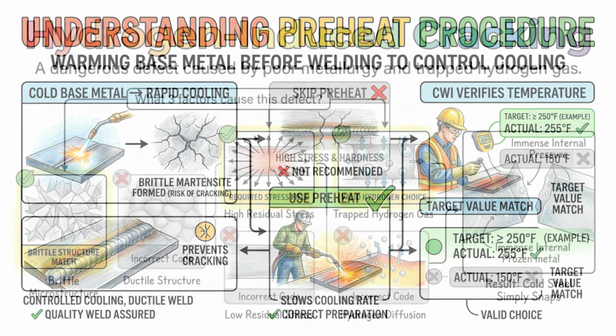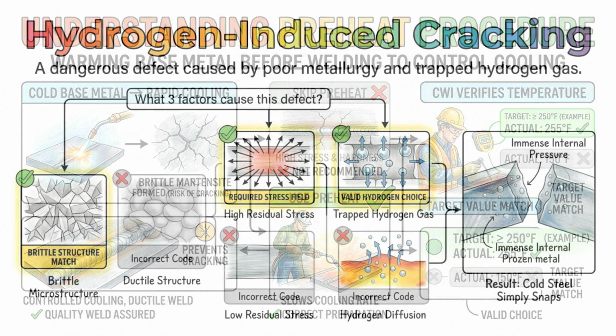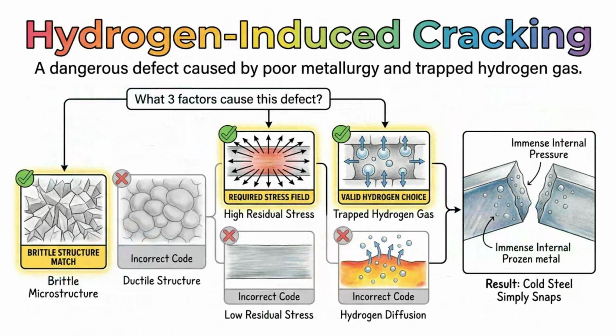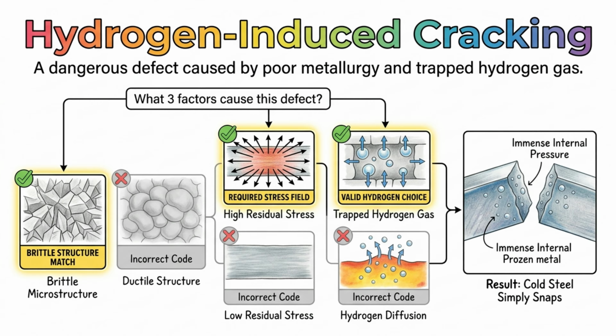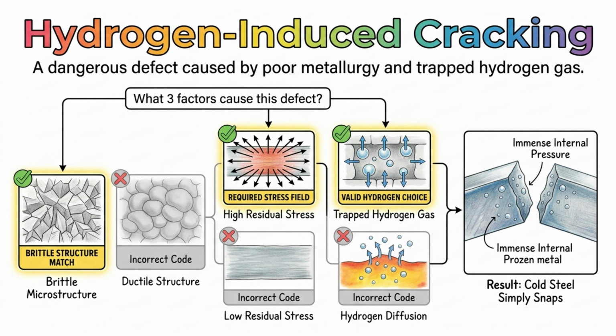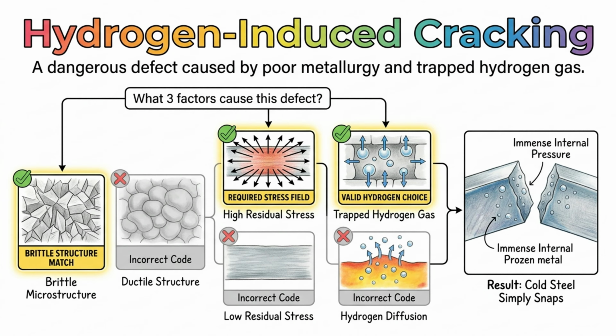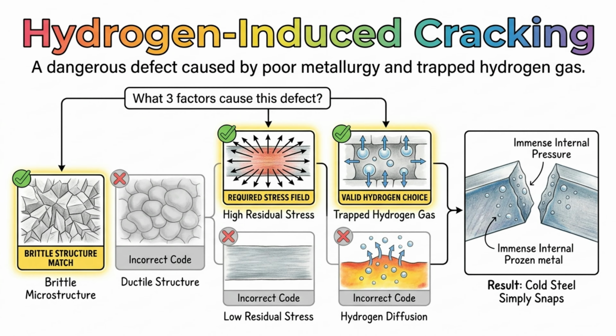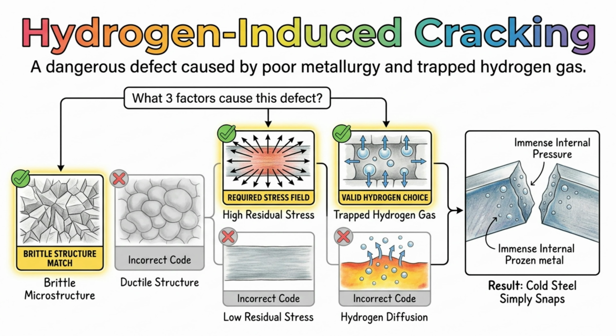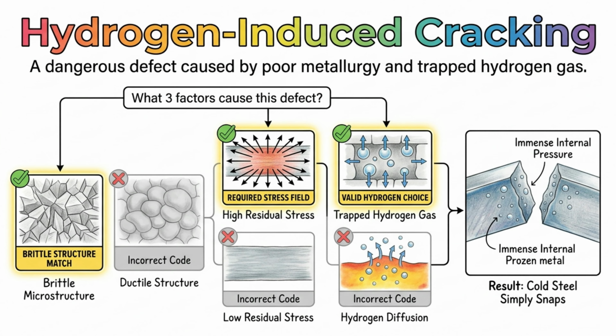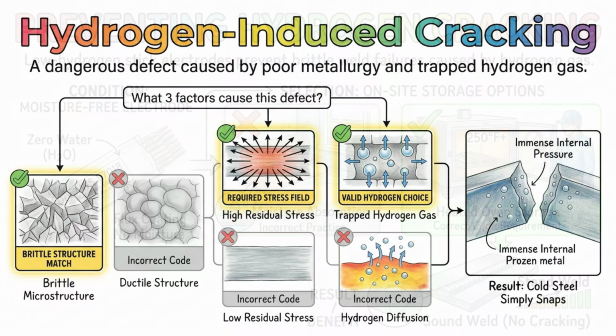One of the most dangerous defects caused by poor metallurgy is called hydrogen-induced cracking. For this specific crack to form, three things must be present at the exact same time, which are a brittle microscopic structure, high residual stress, and hydrogen gas trapped inside the metal. Hydrogen gas is incredibly tiny and can easily slip into the liquid weld pool, where it gets trapped as the metal freezes solid. Once trapped, the hydrogen slowly builds up immense internal pressure until the cold steel simply snaps.